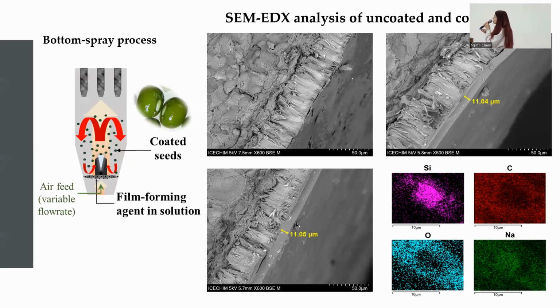And as you can see, we obtained by SEM analysis a homogeneous film with or without silica nanoparticles. Based on EDX analysis, the main elements are silicon, carbon, oxygen, and sodium. The film is about 11 micrometers thick.